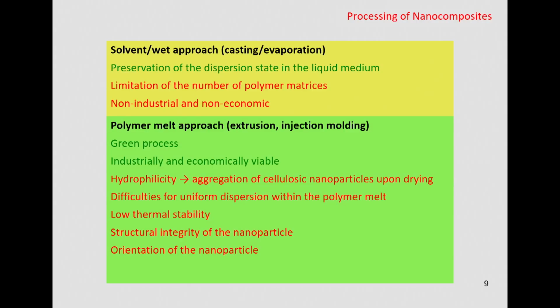I mean by green process that no solvent is involved. Of course, it's an industrial process, so it's economically viable, but you can see that there are several drawbacks. Hydrophilicity. It's necessary to dry the nanoparticles before extrusion. And of course, we can expect aggregation. Then it will be difficult to disperse, to obtain a uniform dispersion of this nanoparticle in the polymer melt.